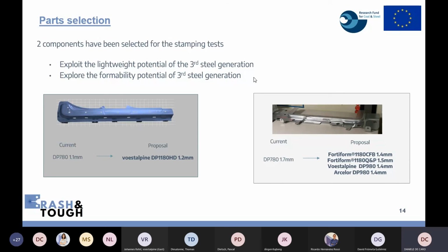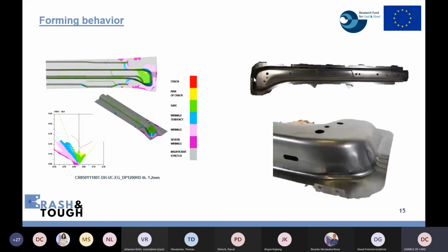The goal of this work package was to understand if with these new materials, so increasing the strength of the material we are using, the component is feasible, so assess the formability in real parts, and so understand which can be the lightweight potential for future application in the new vehicles. Going to the results, before running experimental stamping tests, we performed a feasibility study in a simulation environment, forming simulation, for both of the components. This forming simulation has been done on the highest strength material grade, so the 1180 high formable grade.